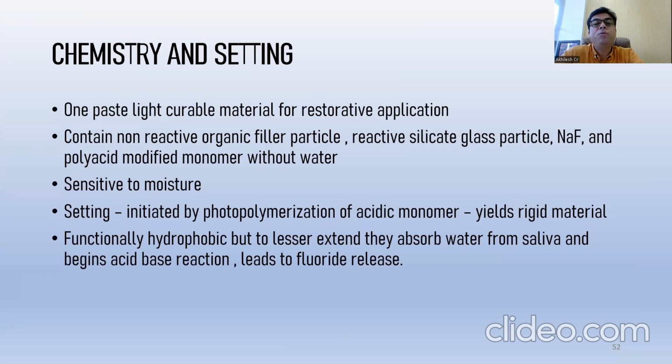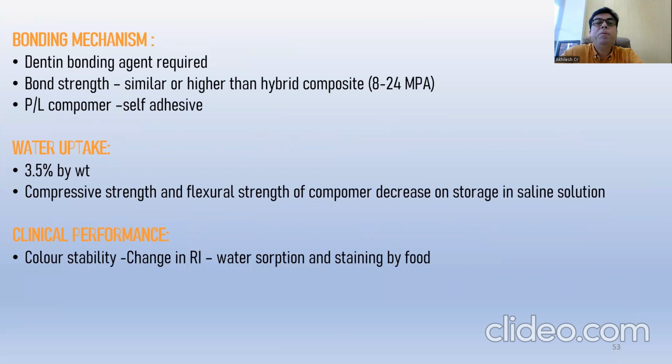Functionally hydrophobic, but to a lesser extent they absorb water from saliva and begin an acid-base reaction. It leads to fluoride release. Bonding mechanism: dentine bonding agent required. Bond strength is similar or higher than hybrid composite, that is 8 to 24 megapascal.